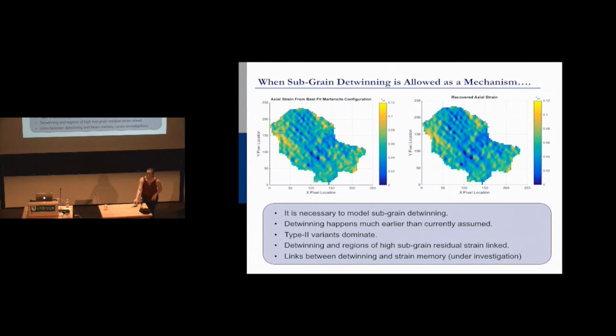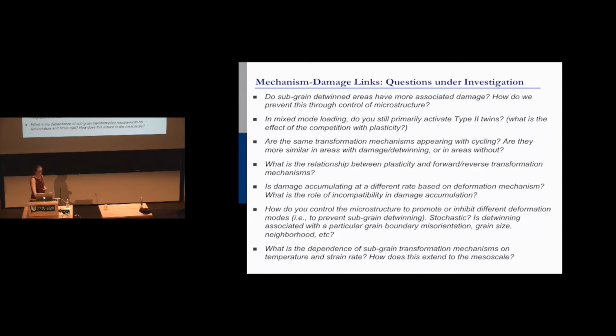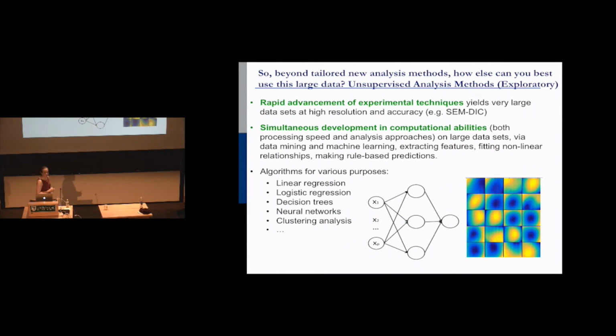So these localized regions of detwinning are very strongly related to residual damage. And there are ways that we're looking at how you tailor the microstructure of these stents so that you don't get this damage. So that you can use these materials, you can torque them up through veins more strongly, you can be more rough on them to get them in a less invasive manner. You can bend them more. And I'm going to skip this because I want to go to learning. I want to make sure we have enough time.